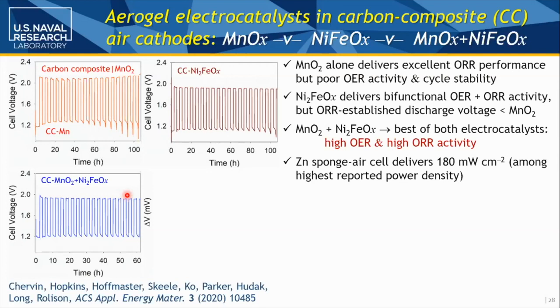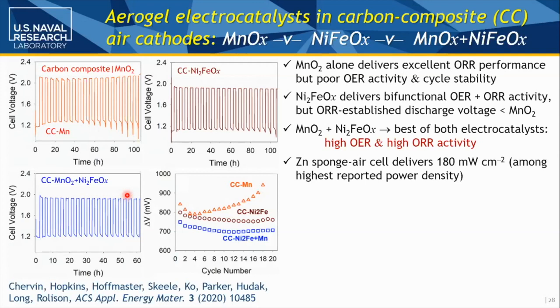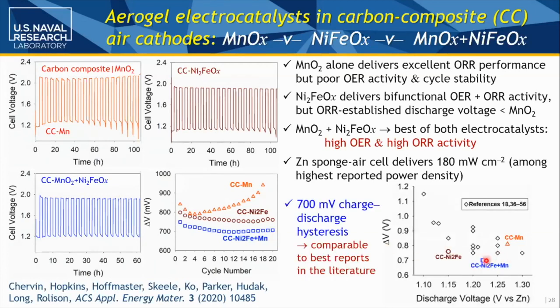We've gotten higher power density out of an architected one, but we're still making that work with 2 types of catalysts in it. And this shows what happens with one alone, just the cryptomelane or the nickel ferrite. And the blue, of course, is the best of all worlds. You've got some of the lowest hysteresis values ever reported. And so here we are relative to what's in the literature. Even just the nickel ferrite alone is not bad on its own. And we never work with cobalt. All of these other ones are typically working with cobalt. And we are trying again to say low supply risk and sustainable.